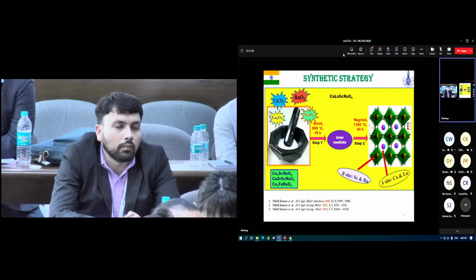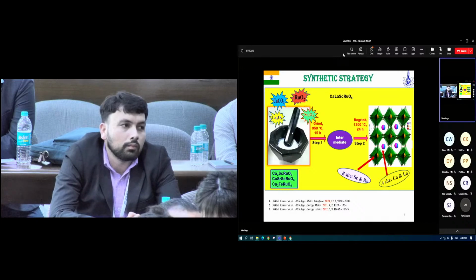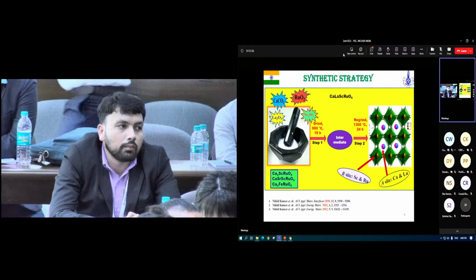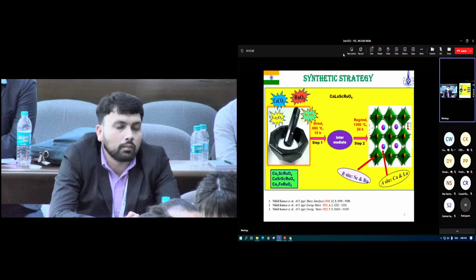Like this, we have made a series of this kind of material, with substitution at the A site by strontium in place of lanthanum, and another material by substituting iron in place of scandium. And we have published all these materials for water splitting reactions.